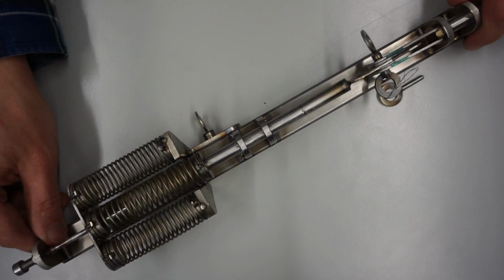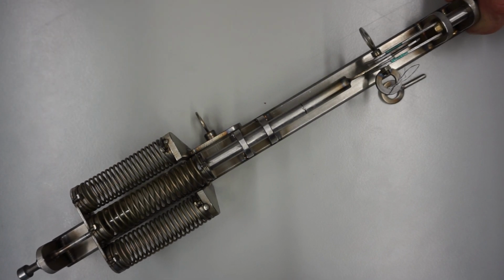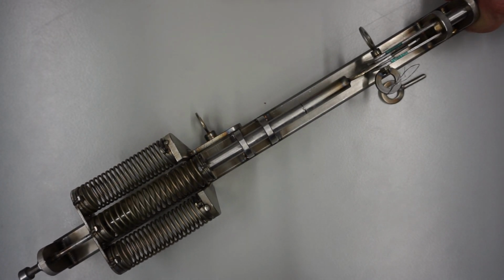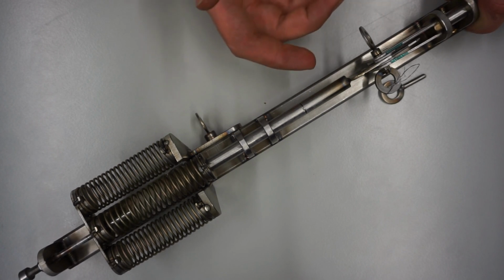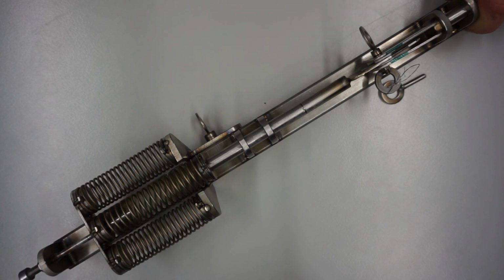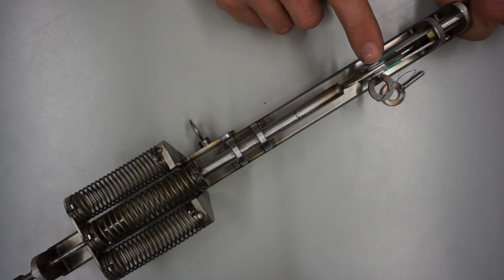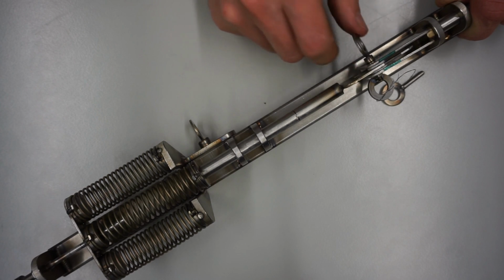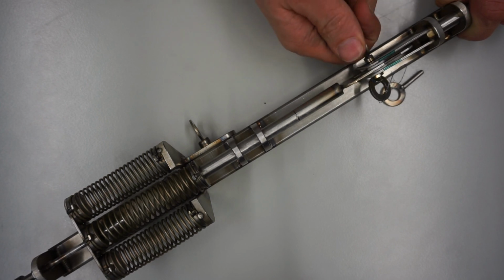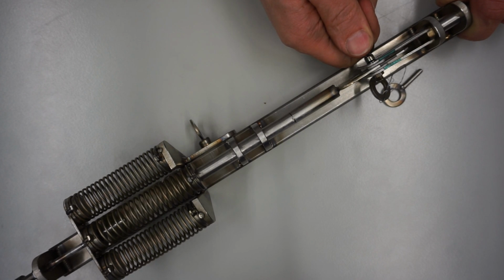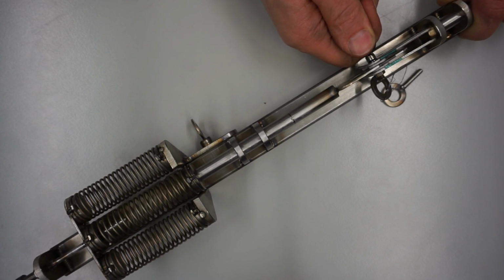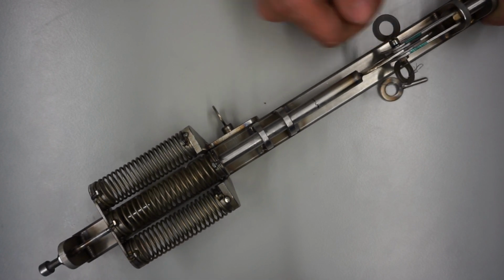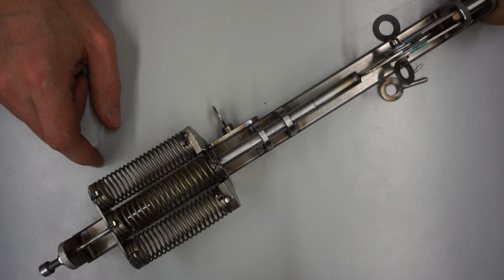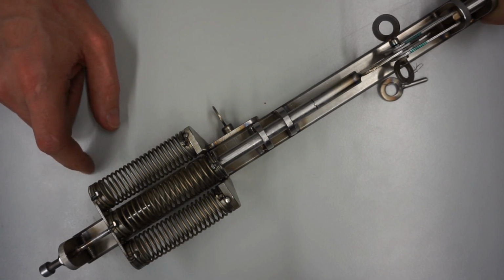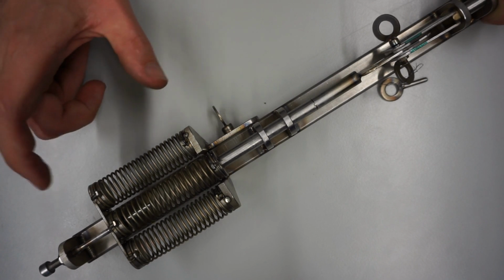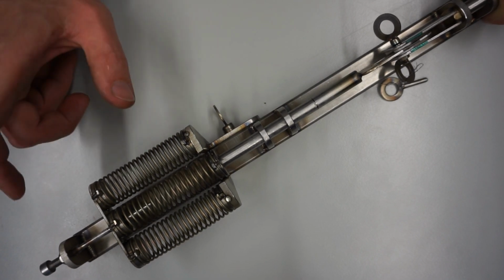Similarly, our welded workpieces distort if we conduct a post-weld heat treatment. Typically what happens during heat treatments is that material loses strength as it gets hot. We can simulate this with decontraction by loosening the screw here. As I do this, you see that the residual stresses relax a little, which in turn causes springing back distortion, here in form of lengthening of our truss. A better term for this would probably be relaxation distortion. There is no bending in this case because our truss is symmetrical.